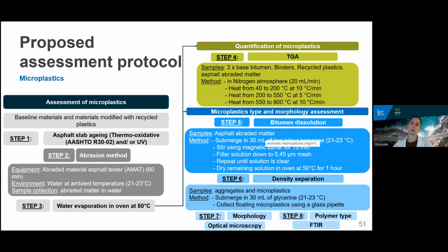So following this assessment for microplastics, we were then in a position to recommend a protocol for their assessment. This protocol involves avenues for both their qualification and quantification. Now, as limits for microplastics have not yet been set, it is recommended that the release of microplastics from recycled plastic modified asphalt is compared against commonly used materials. It is also proposed that the slabs are assessed after simulated aging, either thermooxidative or UV or both.